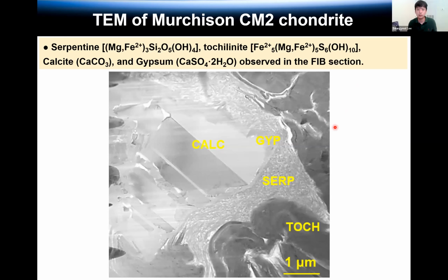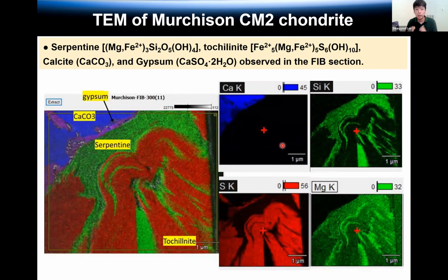Yeah, this is a TEM image of a focused ion beam section. It clearly shows the tochilinite and serpentine, and this is a calcite mineral, and gypsum is also involved here. With the TEM EDS data we can have EDS mapping. Serpentine chemistry is magnesium, iron, silica, and also contains water in the structure. So the silica area leads to the serpentine area, the green area.